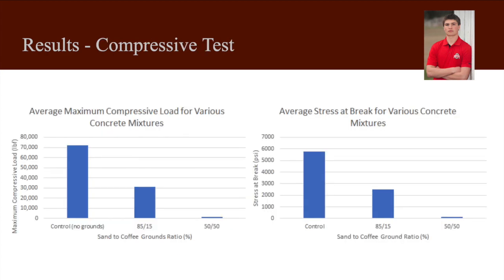Here are a few graphs of the results of the compressive test. Maximum compressive load is shown on the left, while the average stress at break is shown on the right. The control sample took by far the highest compressive load, followed by the 85 to 15 ratio, and then the 50-50 mix. The 50-50 mix had almost negligible compressive strength compared to the others. For the average stress at break, which is essentially the stress at the failure of the cylinder, it showed very similar properties to that of the maximum compressive load. Once again, as more coffee grounds were added to the mix, the strength of the concrete cylinders decreased drastically.